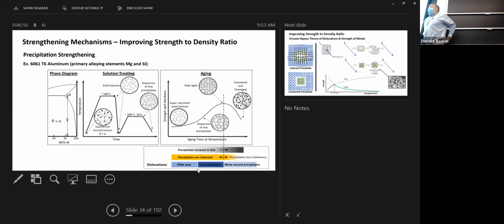This is right about when I started working at this company, and what had happened is that the place that was manufacturing this motor and putting the housing together was taking the aluminum, and rather than heating it up a tiny little bit and then dropping the stator in, they were sticking it in a furnace, and it was staying there as long as 6 hours at 400 degrees Celsius. Okay, so we looked at the microstructure, the precipitates were visible, they're huge, and that's why the material failed, because the strength had dropped so dramatically because they overcooked this thing.